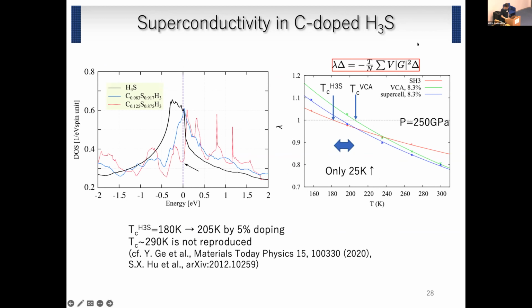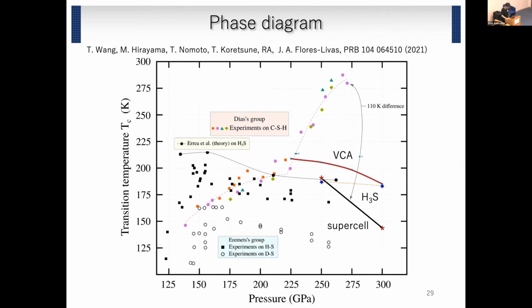And if we solve the Eliashberg equation self-consistently, then at 250 gigapascal there is an enhancement of about 25 Kelvin. But it is not so big, because if we plot the TC of this system, this is the result for virtual crystal approximation, and this is the result for supercell calculation. We see that these TCs are much lower than the values in the paper of Professor Dias. So this is also, I think, an interesting result.